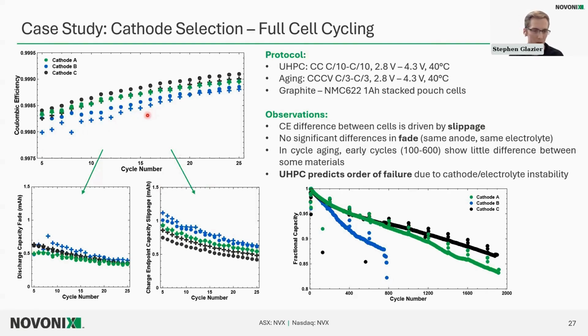So when we split this out into the components of coulombic efficiency, we see that the capacity fade of these cells that we've made, these are 1 amp hour pouch cells off our pilot line, is more or less identical after 20-25 cycles. But we have this big contribution to this lower coulombic efficiency coming from this term that's associated with these electron donating reactions: electrolyte oxidation at the cathode, transition metal dissolution, things that the cathode is contributing to the system. And we notice that these rates of reactions are much higher from cathode B, agreeing with our coin cell data that we collected just within a few days of receiving material.